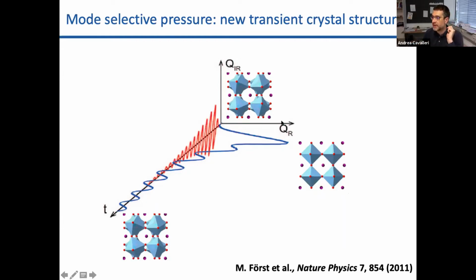So in this plot here, I have plotted the coordinate of the driven mode as a function of time, which comes out here along this coordinate, and the second mode, which here I call QR for other reasons, and that would be uncoupled harmonically, but becomes coupled because of this anharmonic coupling. And because of this coupling, as long as the drive is on, the material will be distorted along the coordinate of the